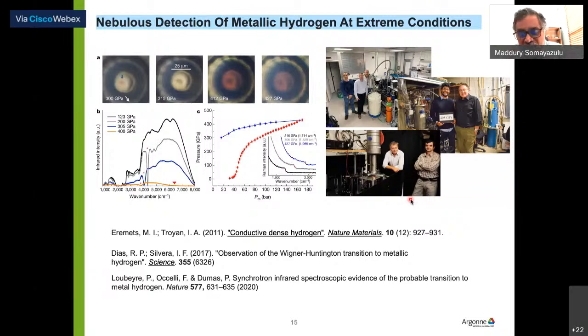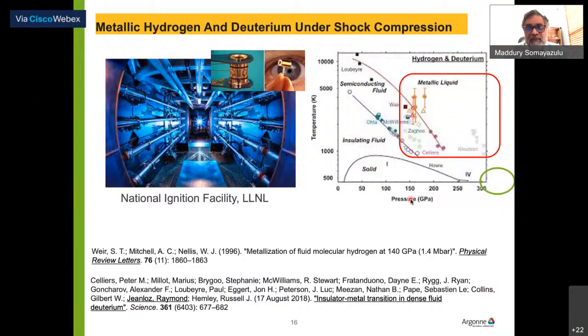But the sum total of all this, over many developments of technologies and many changes in experimental approaches, is that there seems to be a nebulous detection of metallic hydrogen at pressures of the order of, right now, about 450 GPa. Now, is this the end of the story? No, because obviously we still need to understand what Ashcroft meant in his paper. I'll come to that later. But the success in shock experiments has been different. They have been able to make metallic hydrogen and deuterium under shock compression.